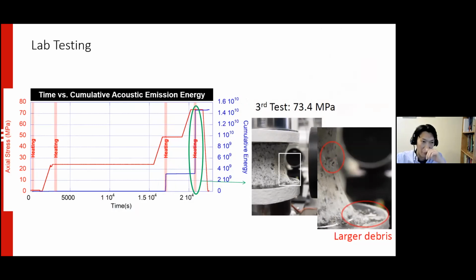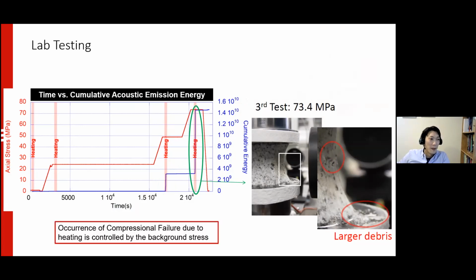What this proves, at least as a proof of concept, is that heating-induced rock failure is a function of the background stress level. So identifying the amount of heating that's required to cause this becomes a measure of stress, or we can infer what the stress magnitude is. The occurrence of compressional failure due to heating is controlled by background stress.